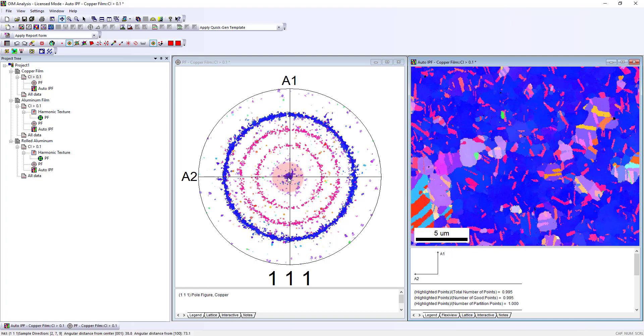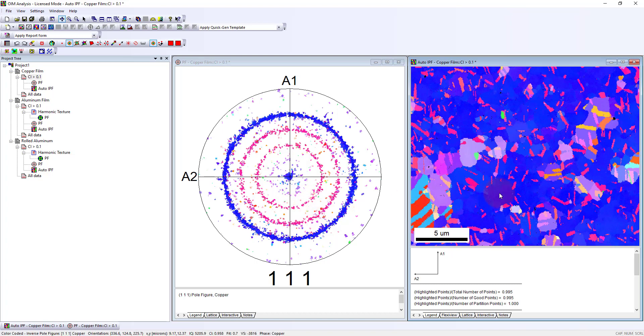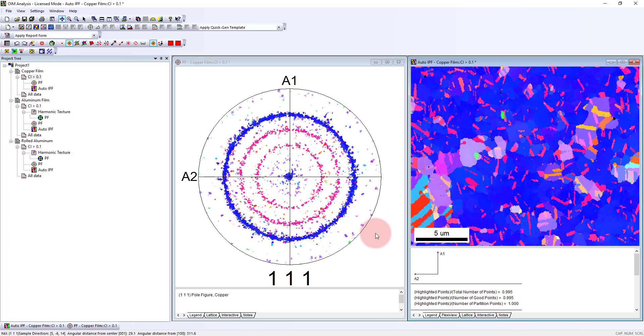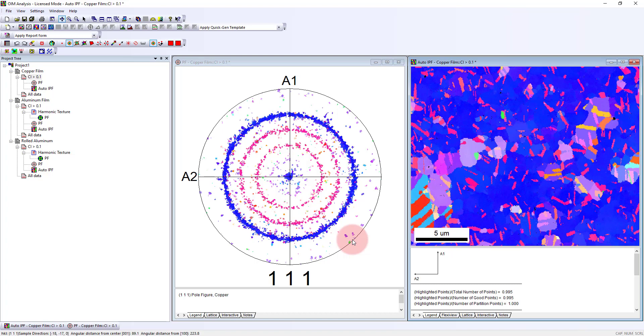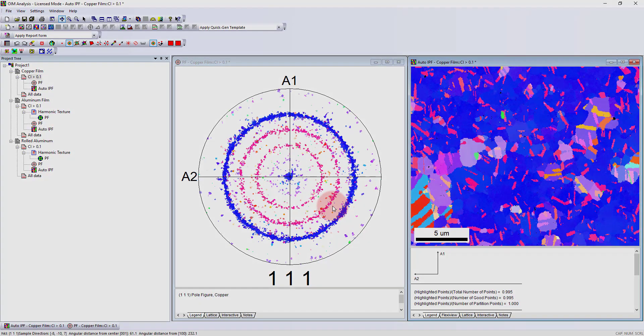The blue fiber texture here is present, but there are these other rings here that show up as the pink colors. Those actually correspond to twins of the original 111 orientation, so we have a twin and then a twin of a twin, first and second order twins. This video shows a few different things we can do to visualize texture via pole figures, do some interactive work, do some highlighting work, and quantify the strength of a texture using the harmonic series expansion calculation of the orientation distribution function.